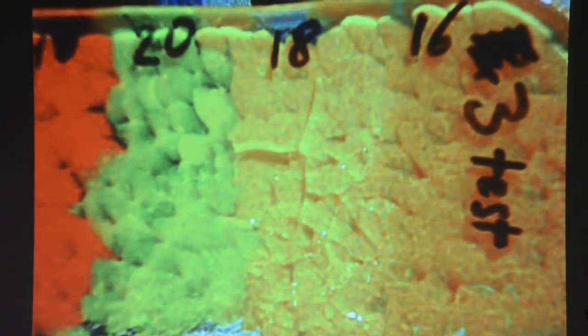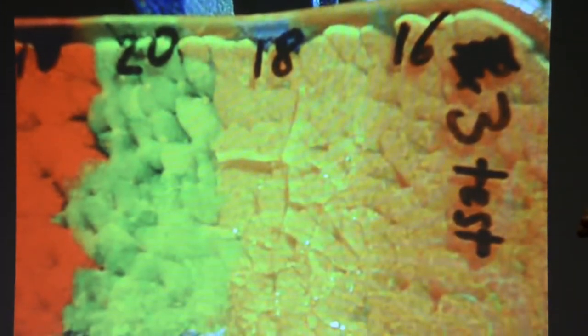If you've overdone it with a large batch of the yellows or the reds or the gold rubies, you haven't really destroyed it, you just bring it back up to really hot, 1400, 1500 Fahrenheit, and you'll redissolve it, and then as you cool it, you can re-achieve your yellow and other colloid-based colors.